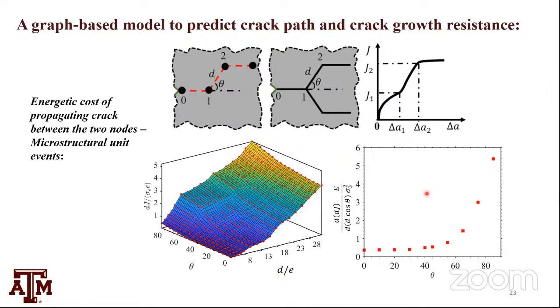Following unit event. It's like analyzing one void ahead of the crack tip, borrowing from what was done by Fred McClintock back in the days, looking at the growth of a void in front of a notch. We're going to analyze evolution of damage in one microstructure feature. So this is what I draw. This is my finite element model. This is simply plane strain 2D.